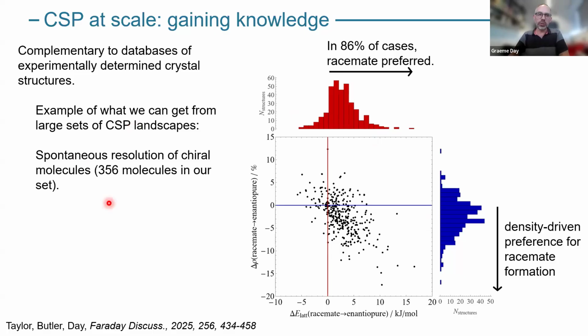We looked at all of the chiral molecules, which is just over 350 of them, and we can start to look at the energy distribution of the difference between the lowest energy racemic and enantiopure crystal structure. In those cases, we can dig into those energetics and really understand what's driving the energetic preference for the racemic structures being lower energy than enantiopure structures, which agrees with what people empirically tend to see. One thing we notice, and it's very easy to analyze, is that most of this is density driven.